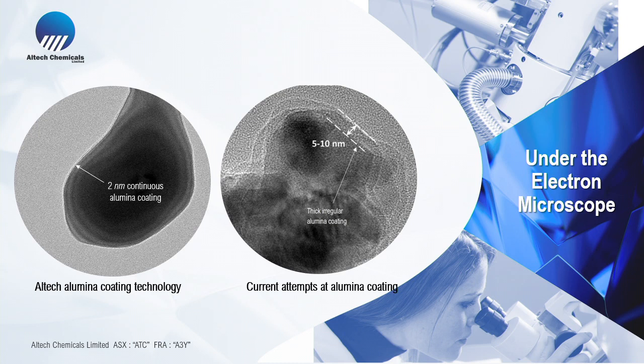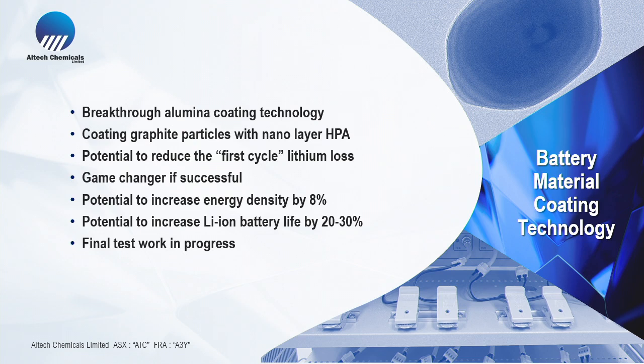We're very excited about the technology, and we think that it's going to resolve the first cycle loss issue, a game changer for the lithium batteries going forward, and potentially increasing the density about 8% and maybe the life 20 to 30% extra life.